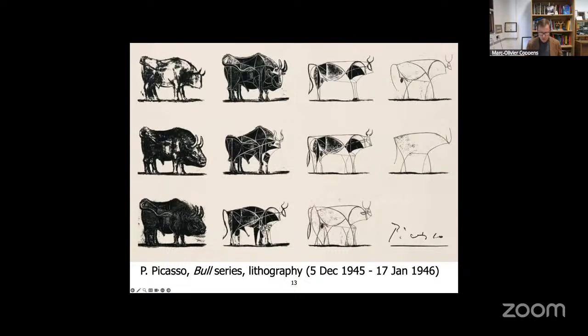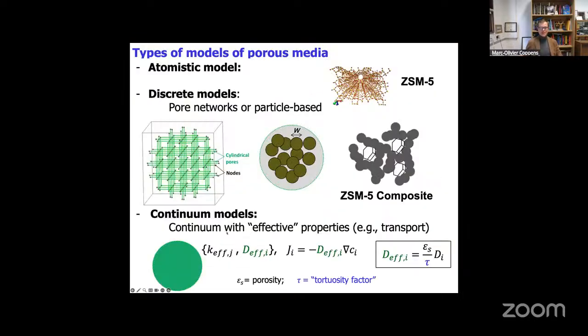So if you go to different types, this is a sketch of different situations. If you have a porous material that is uniform enough, say it consists of nice alumina particles, could be zeolite crystals or alumina particles in this case, a mesoporous material, and it's a single phase, gas phase, or even single phase liquid phase, and porosity is well connected, there is no reason to do more. You can get away with a continuum approach where you can use a tortuosity.